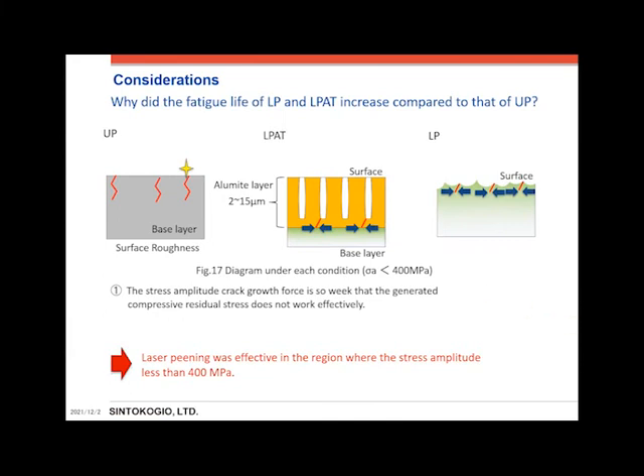So next we discuss why the fatigue life of the LP and LPAT increased compared to that of UP in the region where the stress amplitude was lower than 400 megapascal. This figure shows the model diagram of the crack initiation under each condition. UP does not prevent the crack propagation because there were no factors to inhibit its progress. On the other hand, LP and LP-AT prevent the crack propagation because of the compressive residual stress.